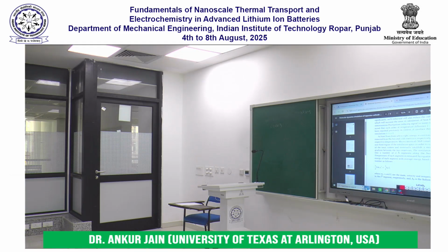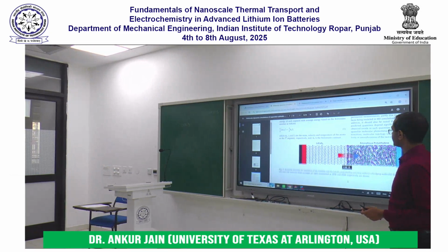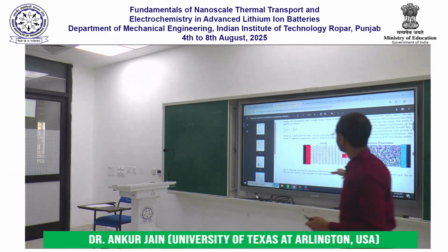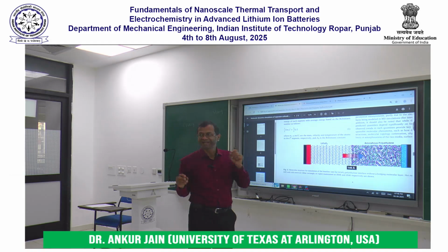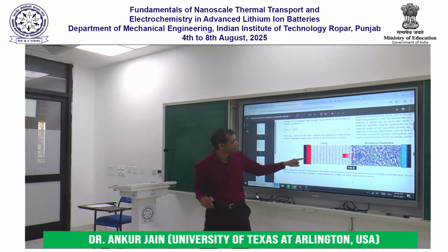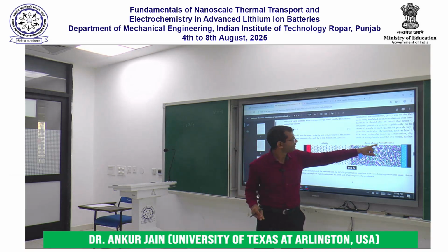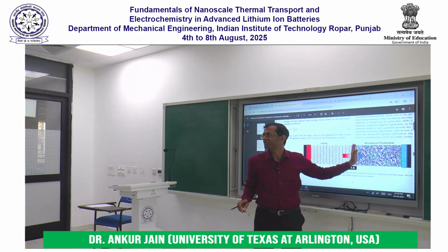I'll show you. So this is the molecular dynamics simulation that we had done. We placed individual molecules of lithium cobalt oxide on one side, which is the cathode, and amorphous polyethylene on the other side, which is the anode, sorry, the separator, right?